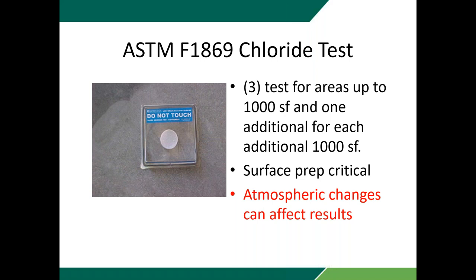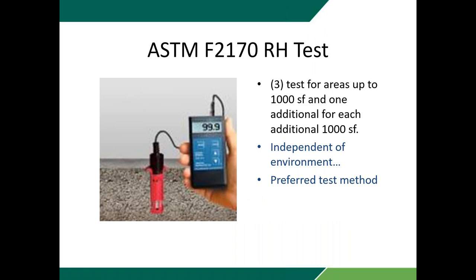So both this test and the visqueen test give us a measure of what the moisture vapor drive is at a given time, but they don't tell us what the moisture vapor drive could potentially be if the atmosphere in the room changes to a point where it results in more of a moisture vapor drive. So I'm thinking most experts say that in 10 years, this test will be phased out in lieu of the relative humidity test. I tend to agree, although I think that probably running both tests together is the best way to do it. However, at some point that is probably going to not be cost effective.